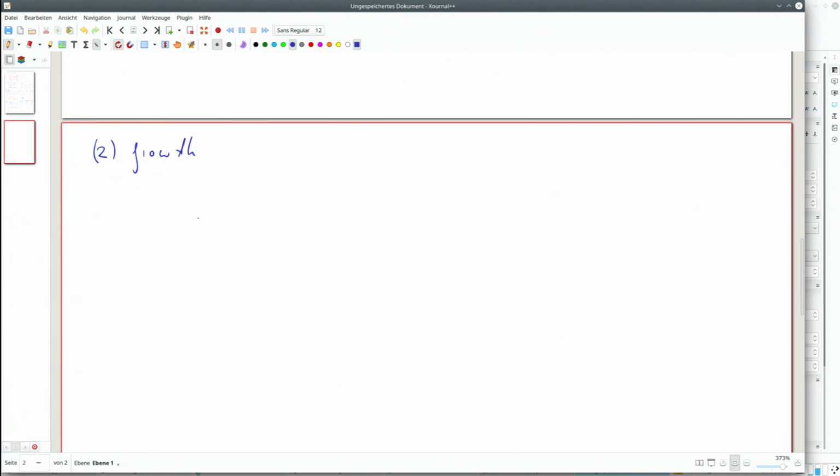again, we can make a very simple model. We look at the cross-section of a precipitate and the B concentration along this cross-section here. Here inside the precipitate, we have the nu beta. Outside the precipitate, that's some kind of assumption. Alpha and beta phase are in equilibrium. So we assume that here we have the nu alpha from the phase diagram. And only at some distance, we go towards the initial concentration.